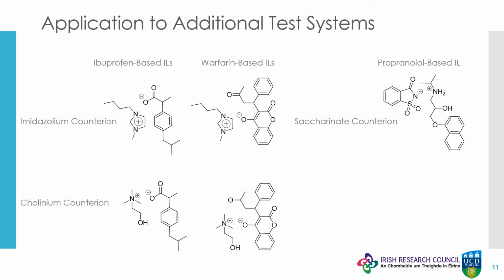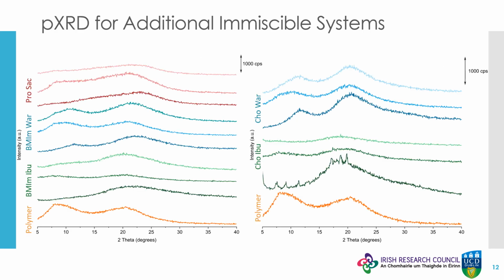With this in mind, a number of additional API-ILs were spray-dried using the immiscible approach to demonstrate its versatility at 50 and 75% weight-for-weight loading in the high molecular weight grade of the polymer. In the diffraction patterns presented here, the pure API-IL is the lowest graph for each example, with the 50% weight-for-weight loading placed above it, and the 75% weight-for-weight loading located above that again. As expected, there is no evidence of crystalline material for any of the products after being spray encapsulated.